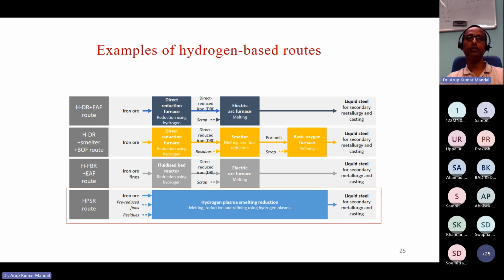Like if you want to produce the DRI, you have to go for the pellet route. Means the mineral after mineral beneficiation, you have to produce the DRI grade pellets, and then these pellets will be reduced and melted in electric arc furnace. But with this hydrogen plasma based smelting reduction, you can treat low grade or high grade or iron bearing waste materials like iron ore slime or iron ore fines, etc. Because here the input material is in the form of fines.